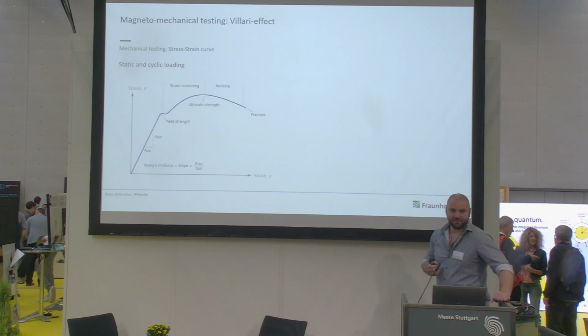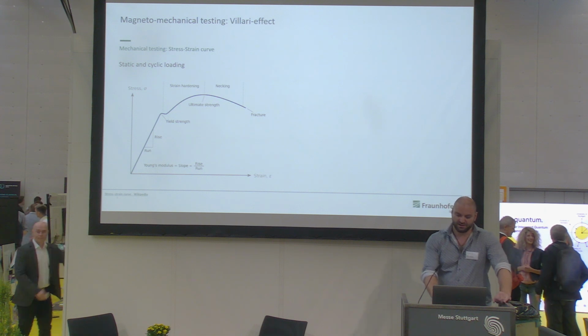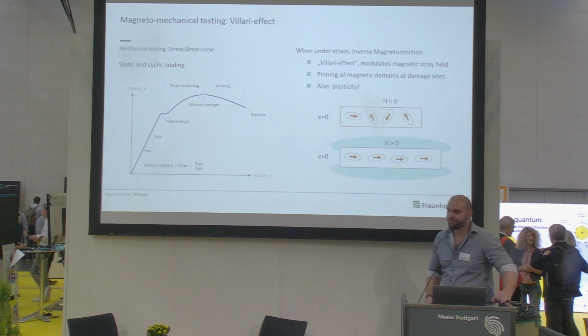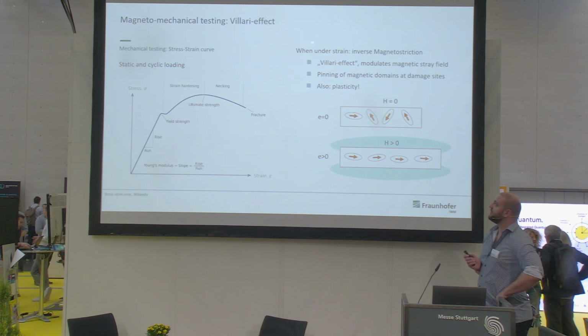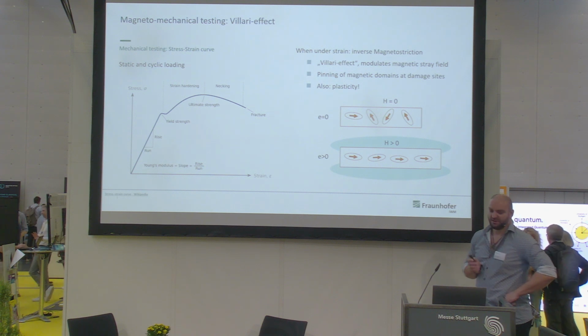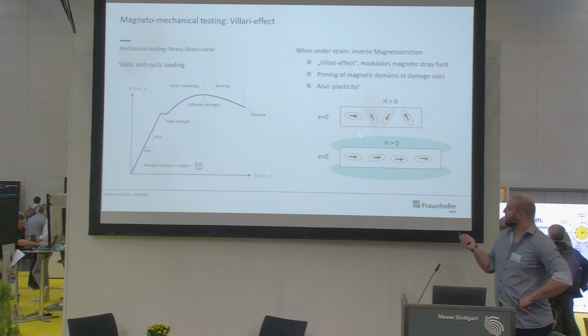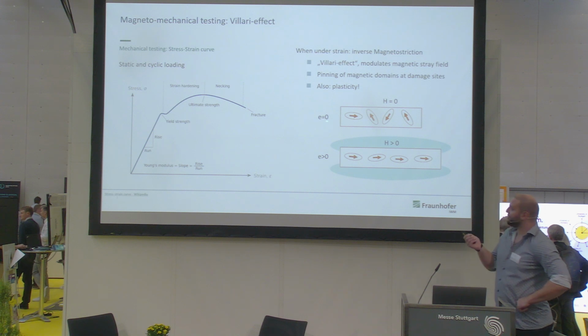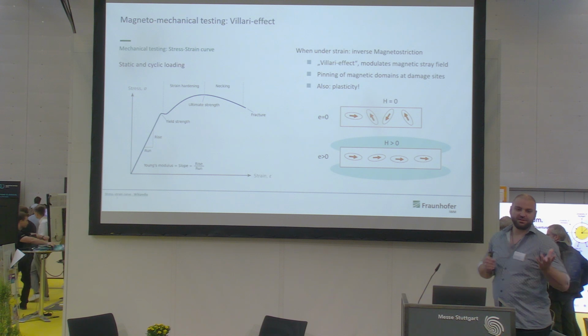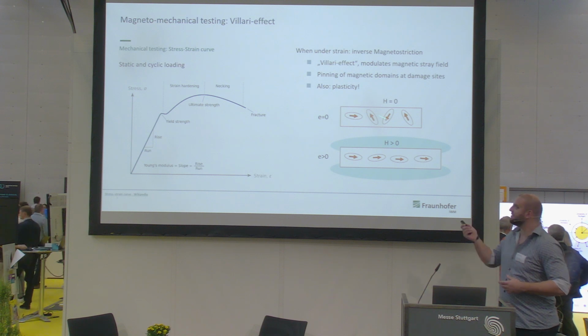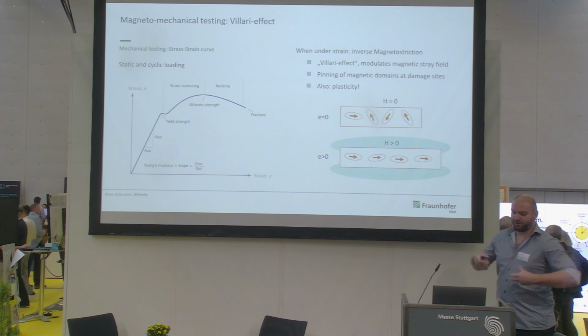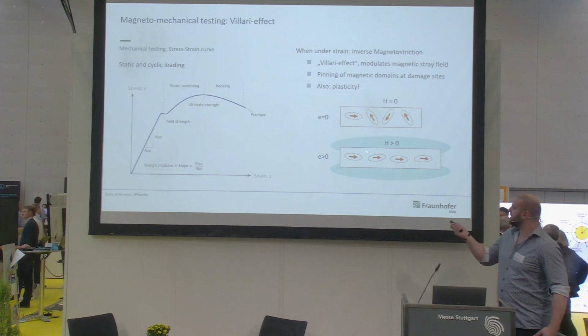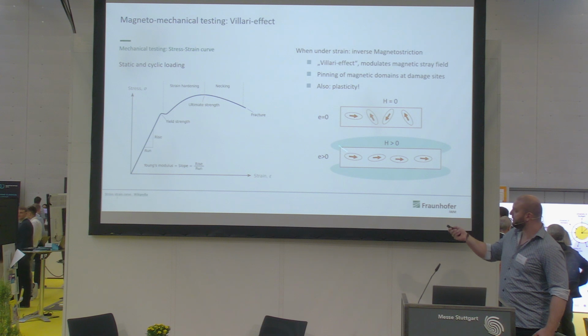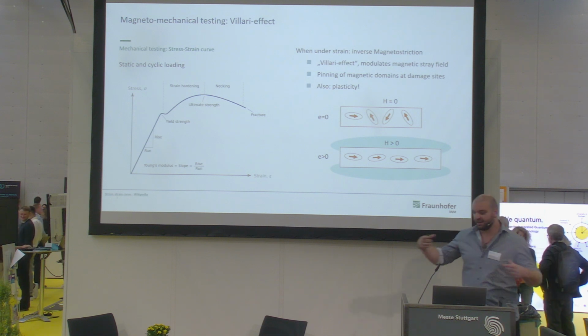Now people have found out that if we pull on a material and it is ferromagnetic, we end up generating a magnetic field. How do we do this? It's called the inverse magnetostrictive or the Villari effect. If we have zero strain applied, we have all the magnetic moments in the material randomly oriented, pointing in every direction and cancelling each other out to zero field. Now if we pull on this material, we apply a strain and elongate the material piece, we generate a magnetic field because all the magnetic moments in the sample are lining up.